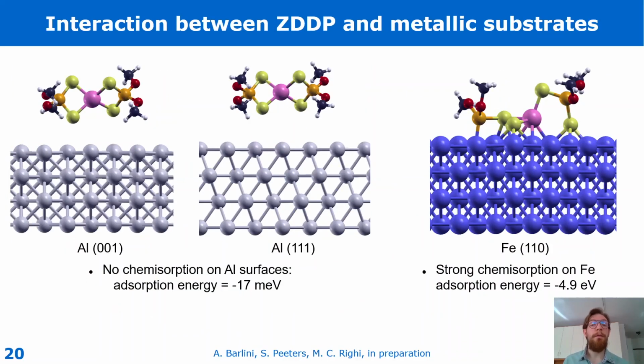Then we consider different substrates. We first consider aluminium. The 111 surface is the most stable, and also we consider 001. And in both cases, you can see that ZDDP is not able to attach to the surface. There is only weak physisorption of just a few tens of millielectron volts. To compare, you can see that with iron, the molecule is not only able to chemisorb, but also decomposes, and so you have very strong chemisorption of around -5 electron volts.